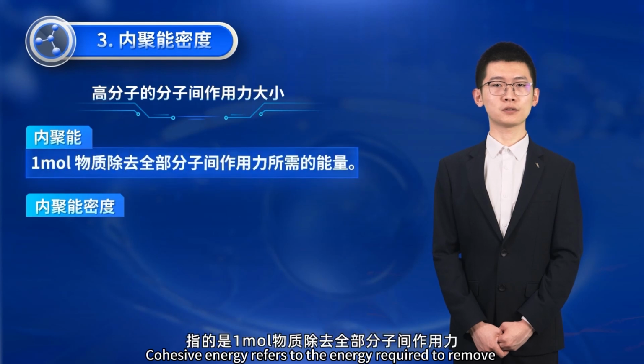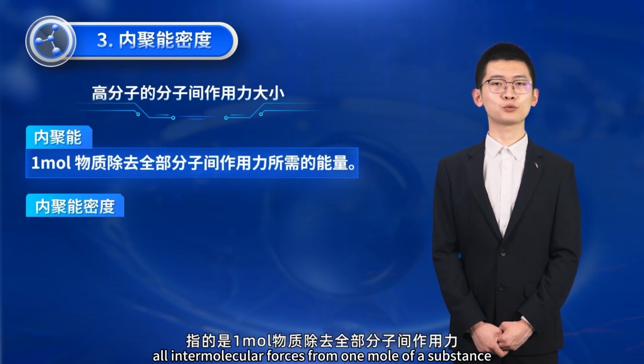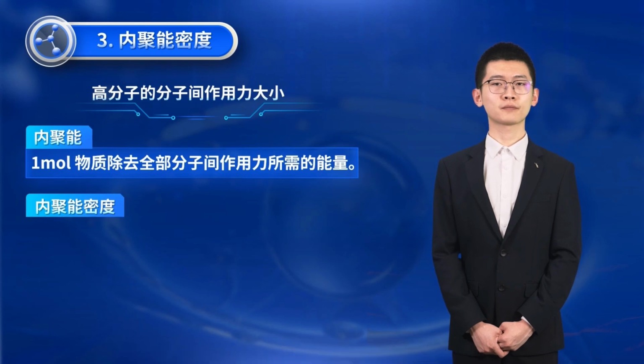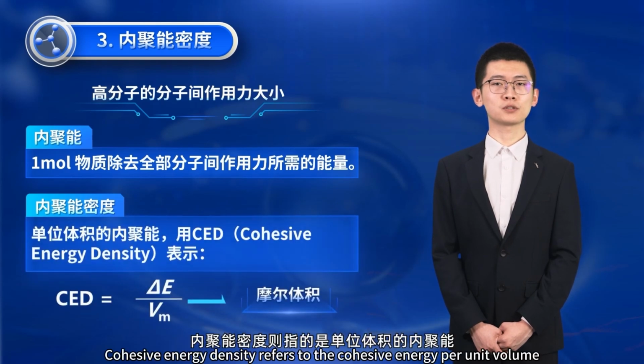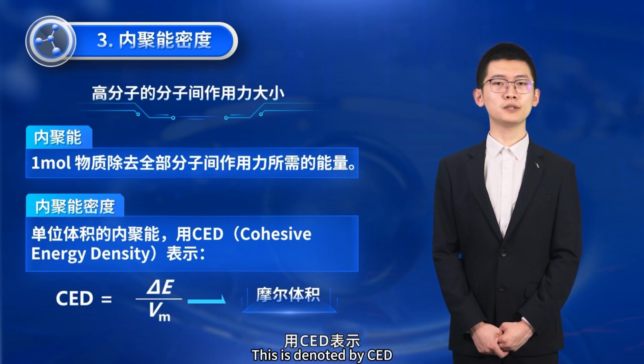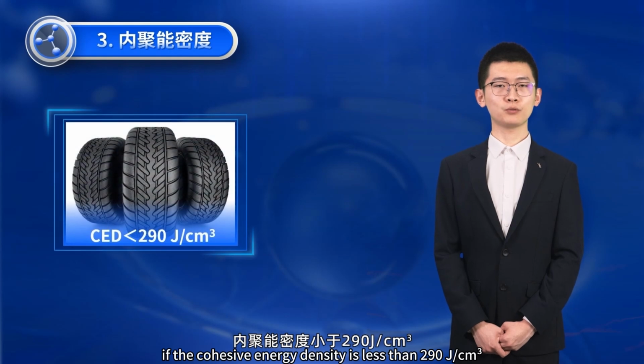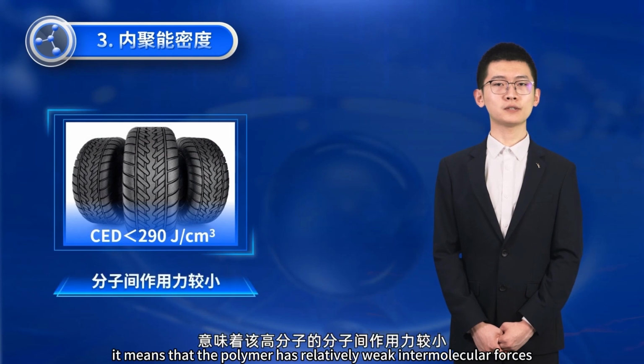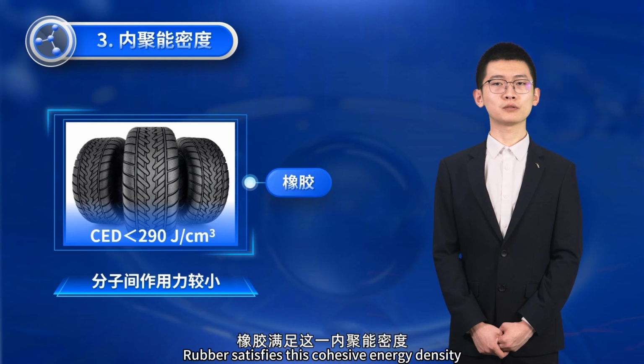Cohesive energy refers to the energy required to remove all intermolecular forces from 1 mole of a substance. Cohesive energy density refers to the cohesive energy per unit volume. This is denoted by CED. In general, if the cohesive energy density is less than 290 joules per cubic centimeter, it means that the polymer has relatively weak intermolecular forces. Rubber satisfies this cohesive energy density.